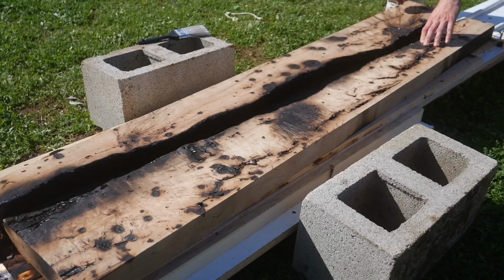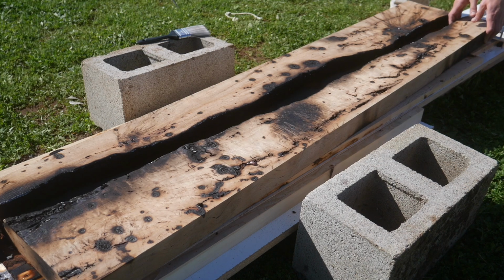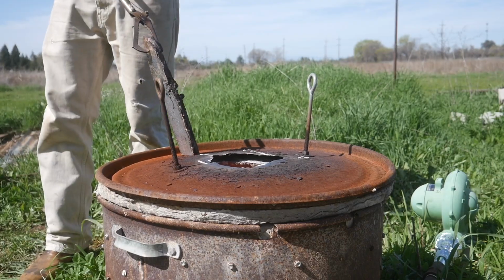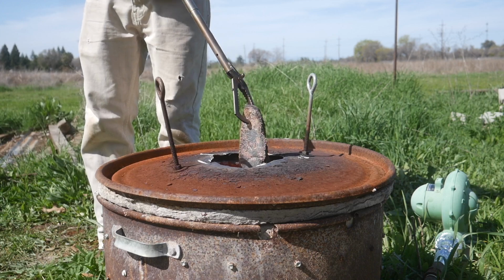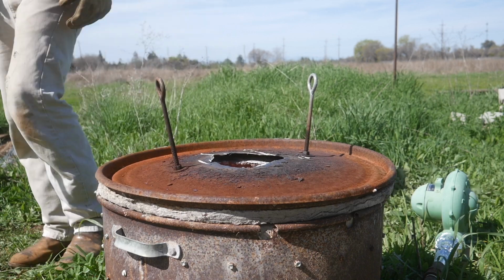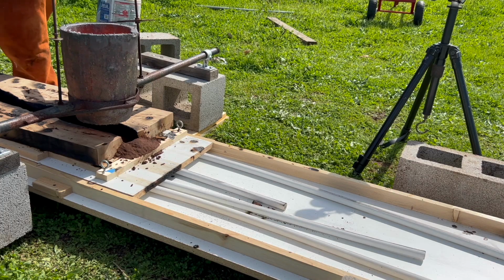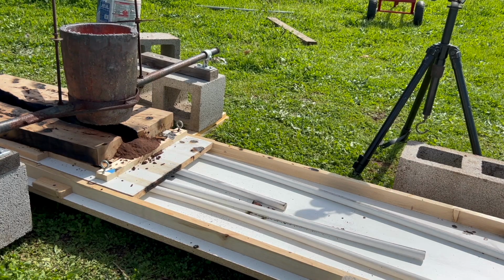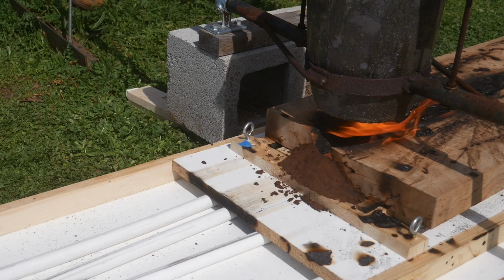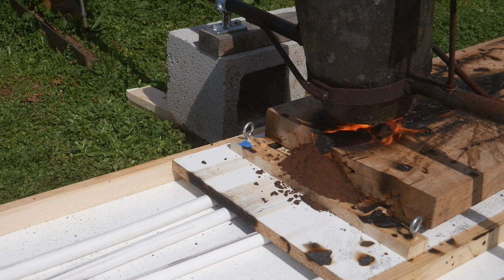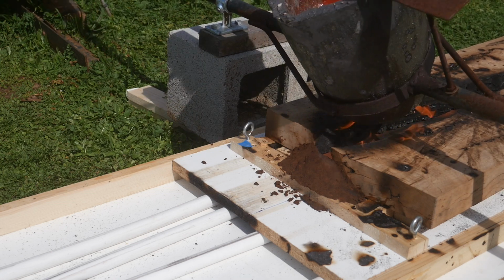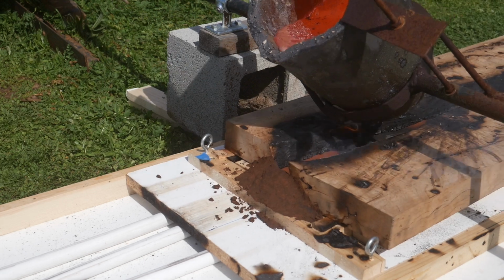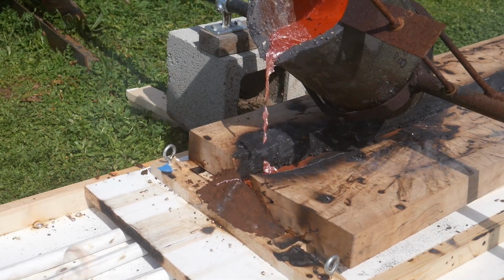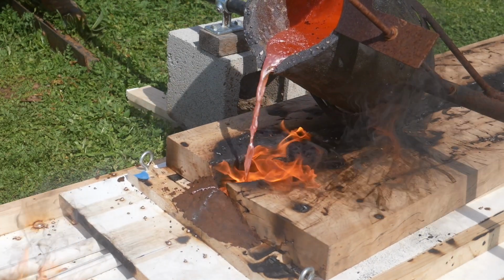the luge. So now we're on to attempt 3, and the wood is charring pretty good, but that's actually a good thing in terms of getting a quality bronze casting. With each failed pour, the wood is charring more and more, and therefore reducing the moisture content on the live edges of the wood. The moisture content in the wood is a large part of what's causing the porosity and any air pockets in the previous castings.